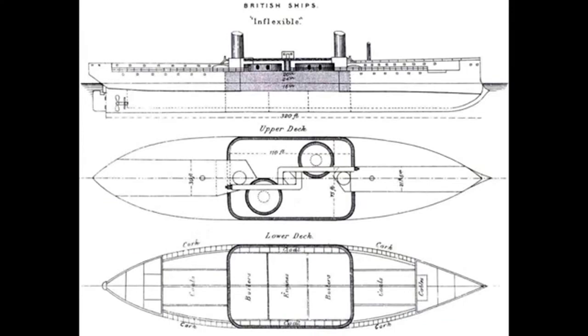By the 1880s, iron plates 18 to 20 inches or even thicker were being used to have even a hope of keeping out the latest high-velocity armour-piercing guns, which had grown from the relatively short 6 and 7-inch weapons of the early 1860s through to the somewhat longer-barreled 12, 13, 16.5 and 17-inch guns that were using ever more powerful explosives to propel their shells through the air. Whereas Warrior and her kin had been fully seagoing, in order to reduce the target area of the ships so as to minimise the space that needed protection, the last ironclads were gradually becoming squatter and less able to handle the open sea, trending more towards giant monitors, purely because of the sheer weight of armour they had to carry.